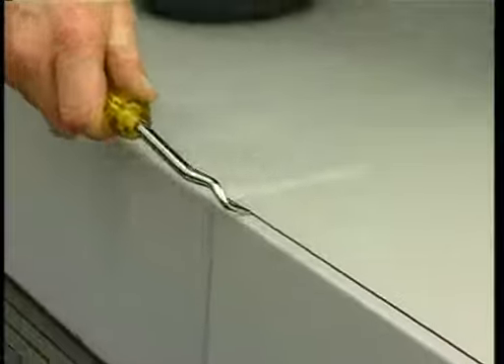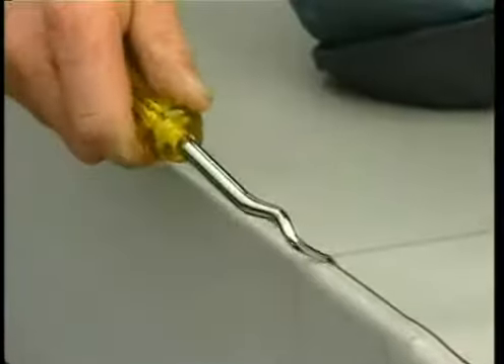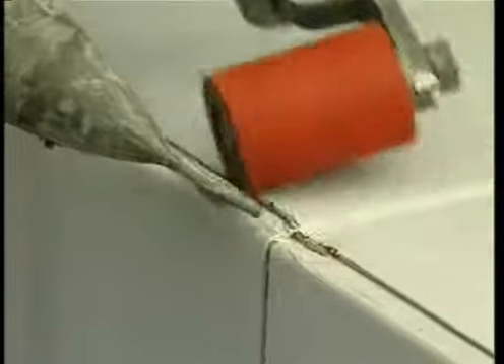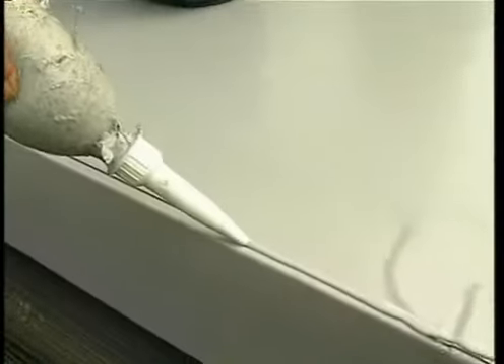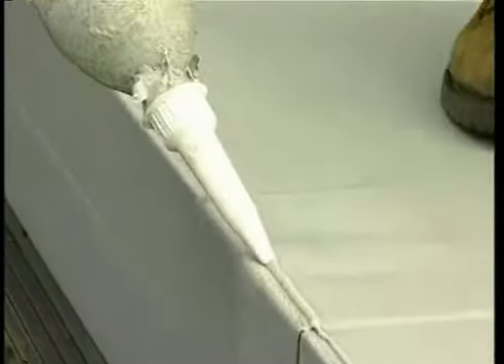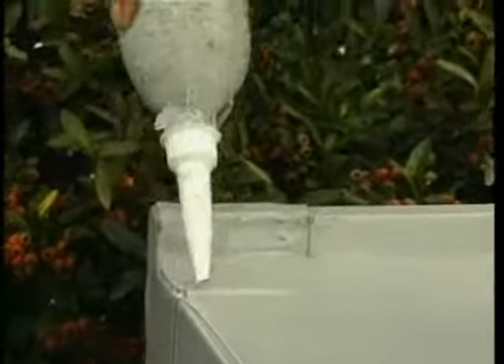After the welds have been made, it's essential to test their integrity by drawing an engineer's scribe along the length of the seams. Any areas that require attention are completed with the hot air gun. Once checked, the seams are sealed with liquid PVC. It's important that this is completed before the surface of the sheet has become contaminated or dusty.